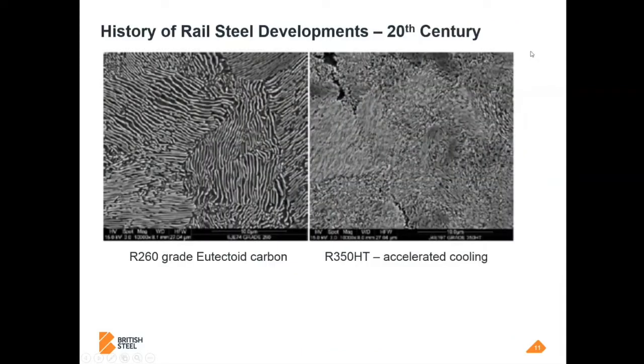Okay, in the late 20th century then, we get to the eutectoid point carbon level, so fully pearlitic rail steels. Typically Scunthorpe R260 grade rail steel is 0.73 to 0.75 carbon level. Fully pearlitic, as I mentioned, and when this grade was originally created, it was seen as wear resistant, as a premium rail steel. But as things have moved on, this has become the standard grade, if you like, and probably 80 to 90% of everything we produce at Scunthorpe is R260 grade. It's the dominant rail grade across Europe, and a lot of our export orders as well.